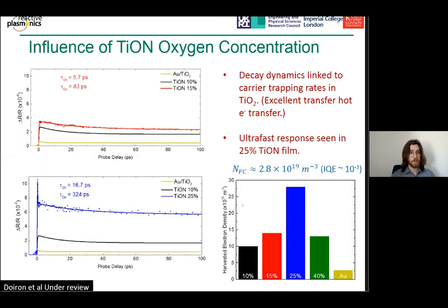We're currently working on this to understand how the variation in oxygen content within these films can allow us to control these hot electron injection and can be used for practical devices. So we see here, we've changed the oxygen content in these titanium oxynitride films, and we have the best response for 25% titanium oxynitride films. So these will allow us to harvest hot electrons most effectively with this oxygen inclusion.